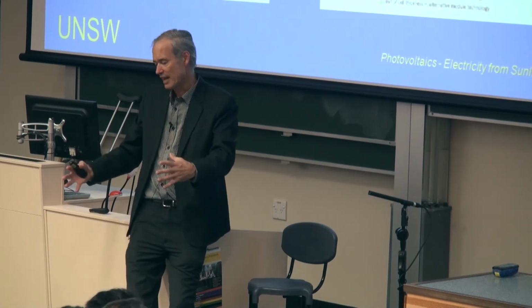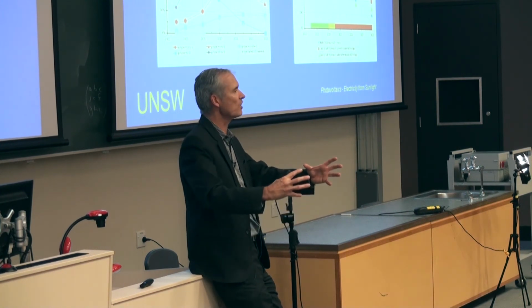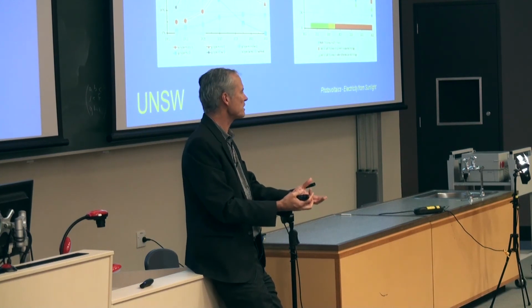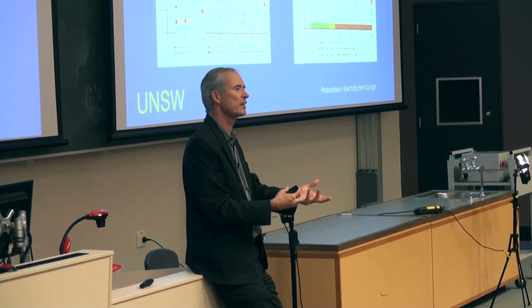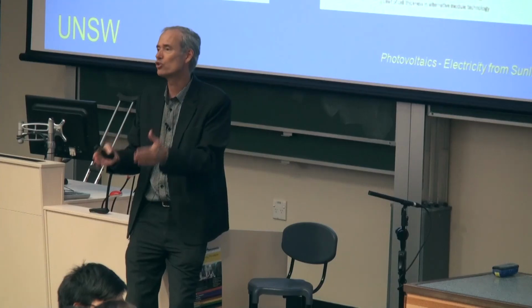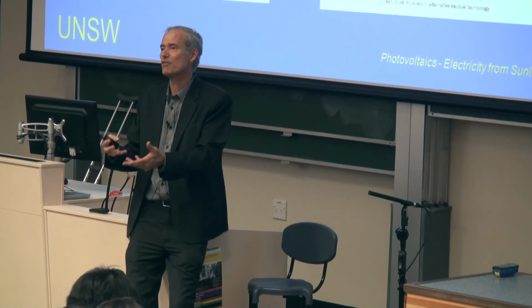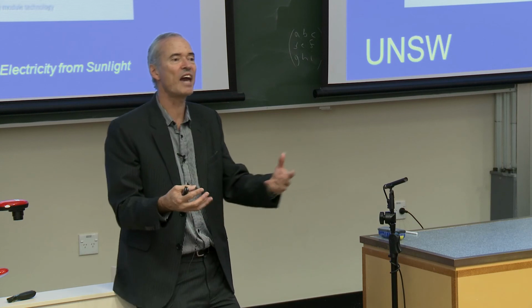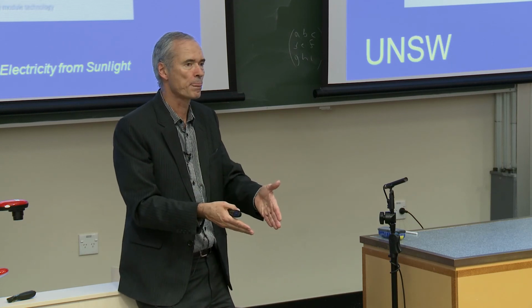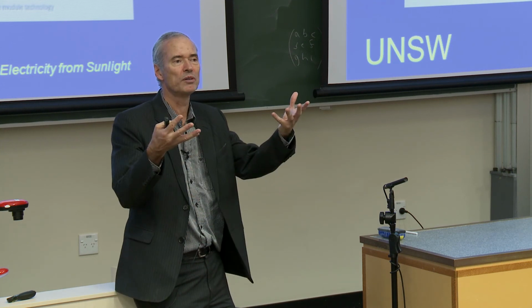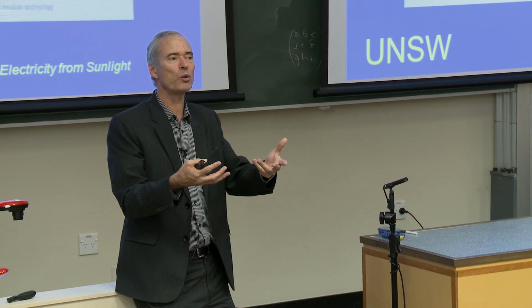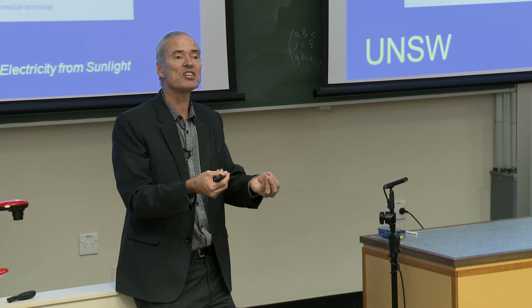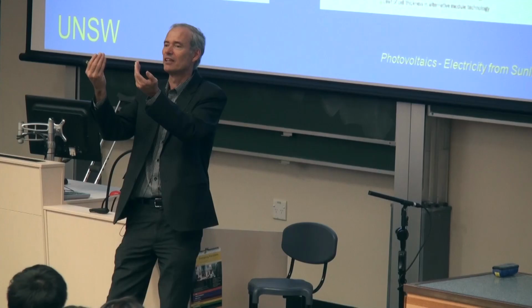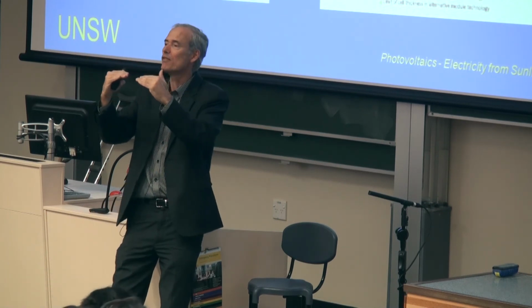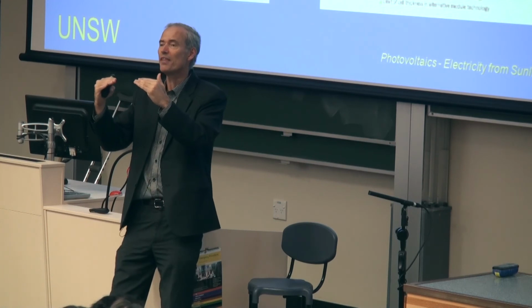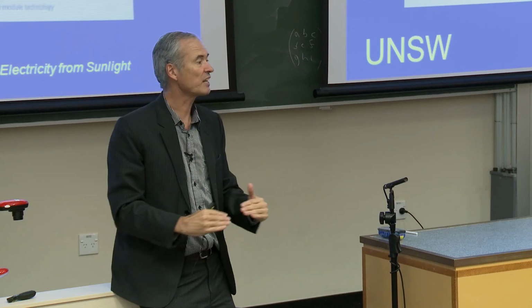One of the problems is that as this ingot of silicon gradually crystallizes, you get a lot of stress accumulating within the silicon material because there's a change of density during the solidification process. Molten silicon has a different density to crystalline silicon. So the growth process involves not just the phase change, but the density change and an accumulation of stress in the silicon material. Now, if you're growing a single crystal, you just keep accumulating stress to the point where you start generating dislocations in the silicon. Those dislocations then propagate right through the whole rest of the ingot that you're growing. And by the time you get to the top, you have a very, very high density of defects to the point where that silicon is much, much lower in quality than the silicon that started at the bottom.